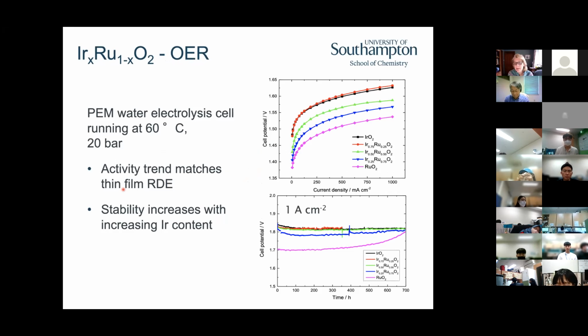We can make these samples up into a proper water electrolyzer cell. This was in collaboration with a company called ITM Power. And we ran the experiment at 60 degrees C under 20 bar. So it's a pressurized cell. And they're only interested in high current density. So this is 1 amp per square centimeter. What you can see is that the ruthenium is indeed the most active material. It requires the least overpotential to get the greatest current density. And iridium sitting up here. But again, our mixed materials are sitting somewhere in the middle. So the trend is still there.